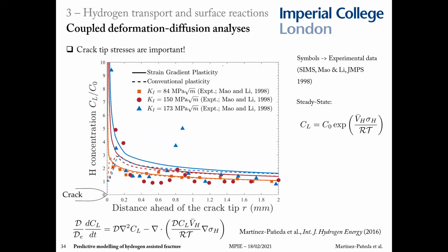And one more thing on the diffusion side before I move to the fracture process. Remember that mechanics plays a key role. There's a hydrostatic term here. And in fact, for the steady state case, this is the closed form solution for the lattice hydrogen concentration. And you can see that there's an exponential dependence on the hydrostatic stress. That is why it's so important to enrich continuum models to be able to accurately quantify crack tip stresses.